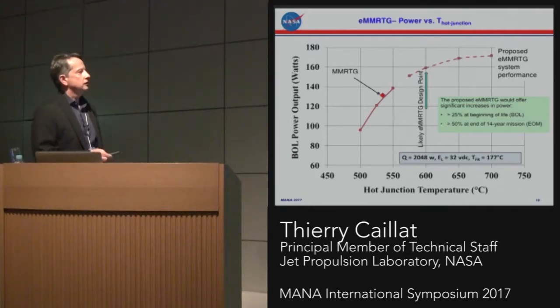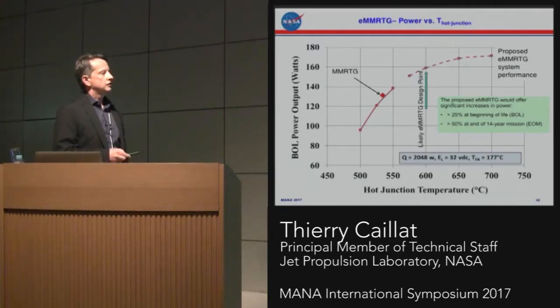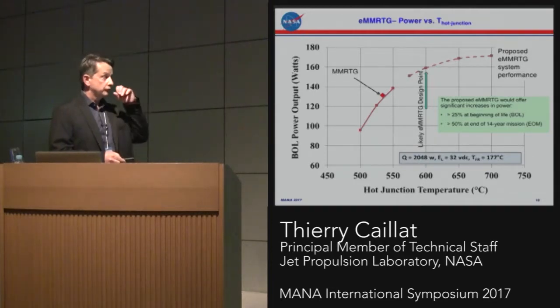So when you're looking at this in terms of the power output of a generator, this is where the MMRTG is, and you get some different conditions. This is fuel inventory, how much plutonium-238 is generating, and sort of the load conditions and the environment, the fin root temperature. Essentially, this is how much the MMRTG would put out in terms of the power. The skutterudite system for equivalent conditions would actually be right there at the beginning of life. This is about 25% more at the beginning of life. And we estimate that it actually can generate 50% more power at the end of a 14-year mission with a 3-year storage. So that's 17 years total.